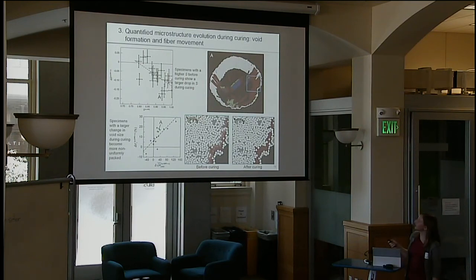So with all of this information about void formation and fiber movement, we can start to optimize this process to have the highest saturation while also having the smallest void sizes, while also having the most uniform fiber bed, which is optimal for later stages.